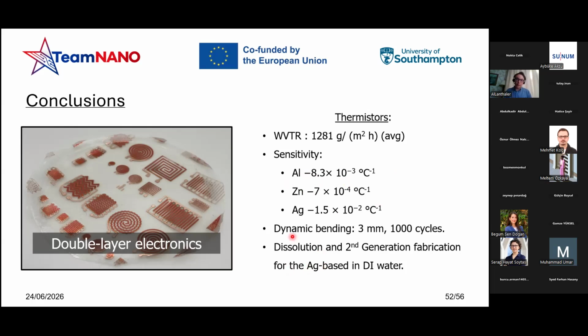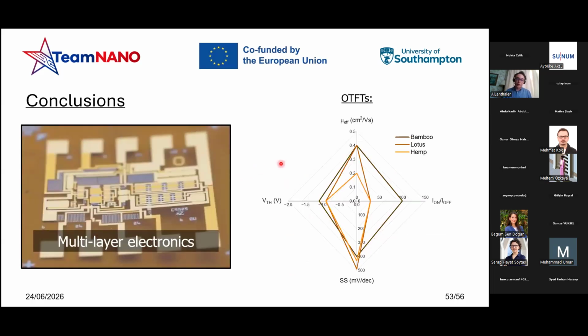The dynamic bending was pretty awesome, I would say, for the silver one, because we were able to withstand a 3 millimeter bending radius for 1,000 cycles, and we were also able to achieve a second generation fabrication process. For the organic TFTs, I made a spider chart over here to sum up everything. As you can see, the best among the others is the bamboo, which was able to achieve higher mobility, lower subthreshold swing, higher on-off ratio, and a threshold voltage of around minus 0.9 volts.